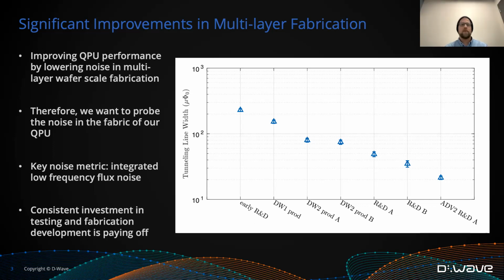There is a lot of work going on to try to understand what the microscopic models are. Some people say that for flux noise, it's oxygen on the surface of your wiring layers, and those can have unpaired spins. So you could make a model based on that and predict what the low frequency flux noise is. There are also models of spin diffusion along your wires, which can also give you low frequency flux noise, so there are clusters of spins. But what we were doing initially was a historical overview of how this MRT technique developed. It just looked at what these tunneling line widths were, and said if you a priori assumed a 1/f type of spectrum, not knowing what the microscopic model is, what would be the line shapes that you get out of that?